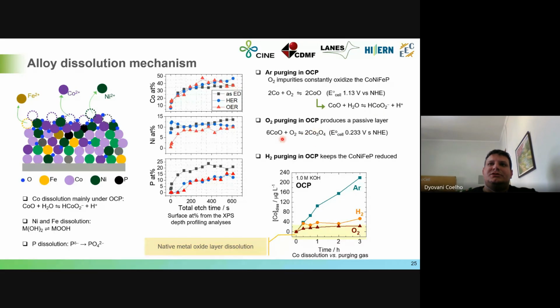If we have oxygen purging during the open circuit potential, or hydrogen purging, we can protect the catalyst. With oxygen purging, we passivate the catalyst surface by the production of high valence cobalt oxides, or, with hydrogen, we protect the catalyst by keeping a reduced environment to prevent the production of the metal oxide. So if we avoid the production of the metal oxide, we can avoid the catalyst dissolution.